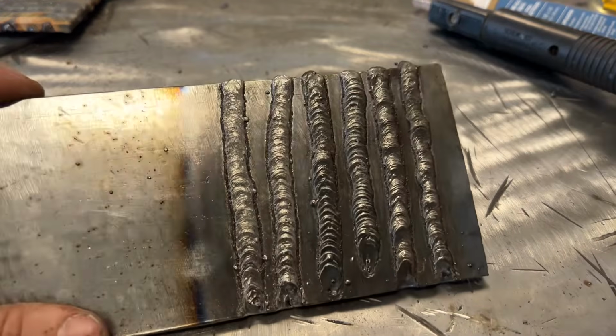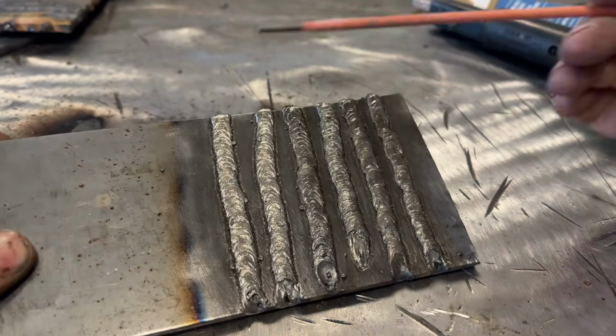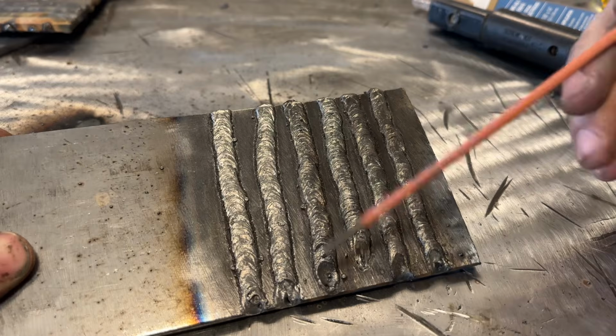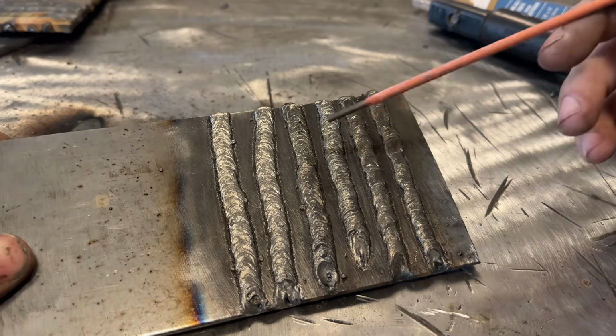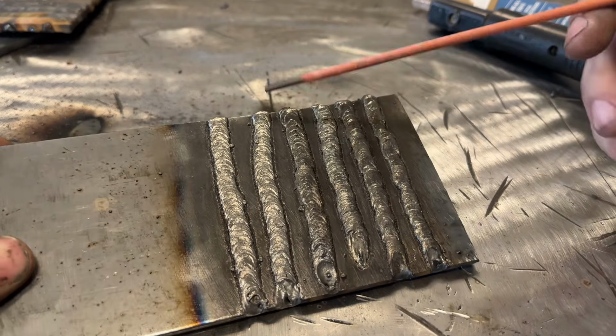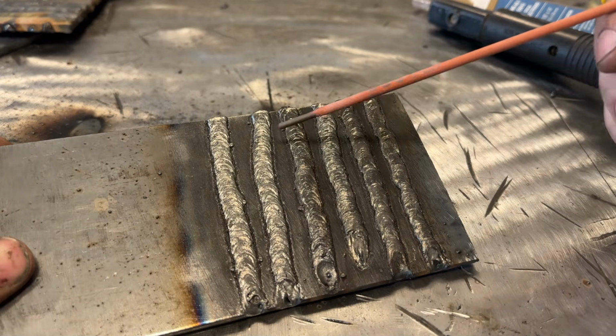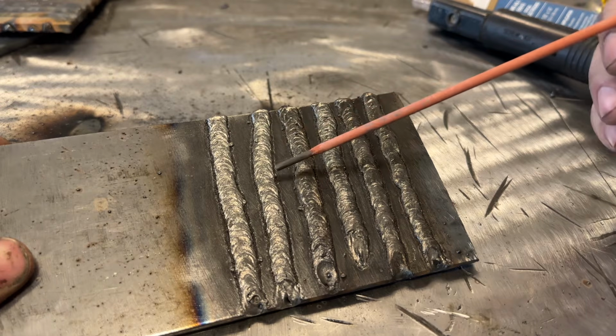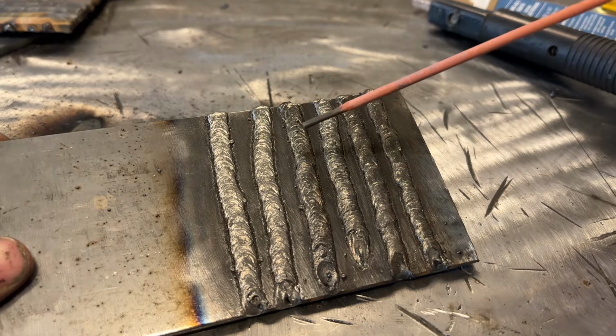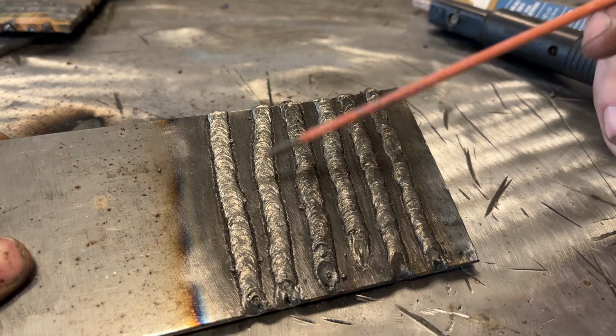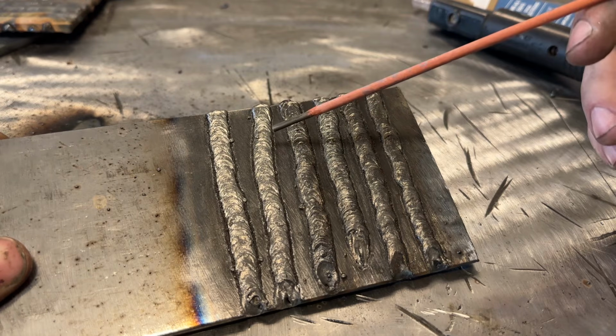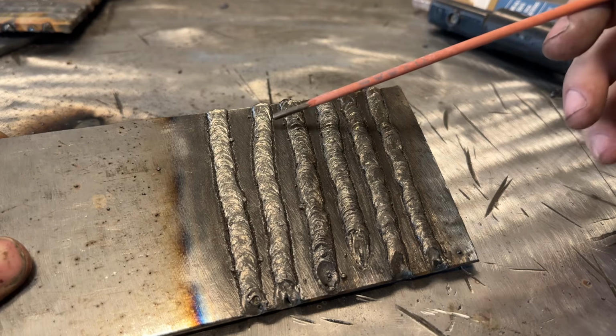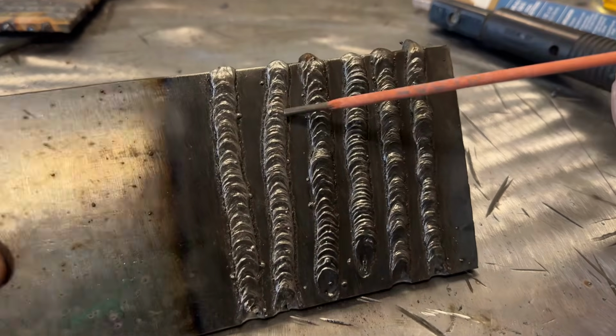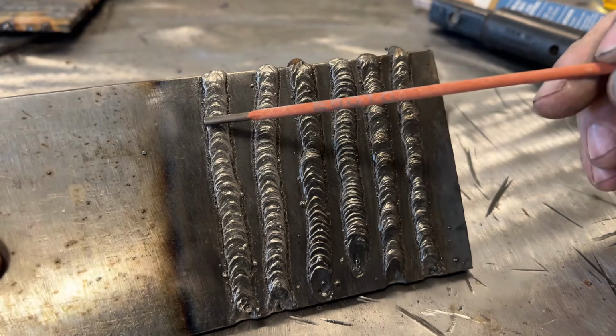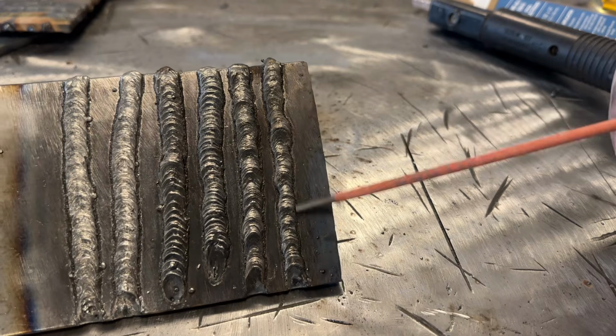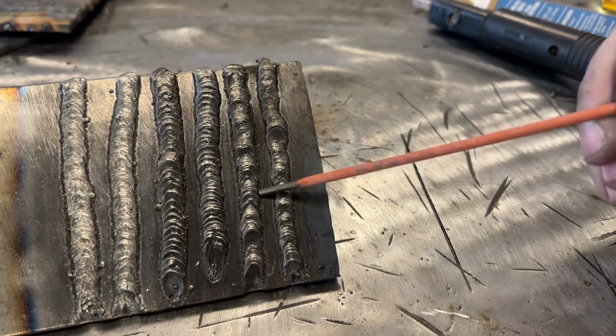There's a couple of other things I'm going to mention here. One is, I know that most of you guys out there are home gamers, and talking about stuff far beyond that may not be of too much use to you, but I will mention when you do welds with 6010 on pipe, it's primarily used for pipe and in-field use. It's very common, like on pipe, to do an x-ray after you finish your welds, and it might even be done between every couple passes, hard to say, but definitely at the end of your job for a particular weld. Well, if you look here, you see this line here along the side of the weld? This one had it really bad. That's still slag in there, okay?